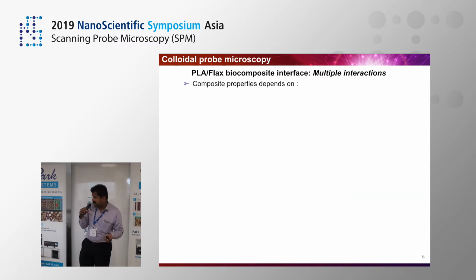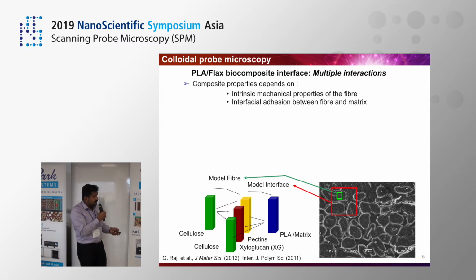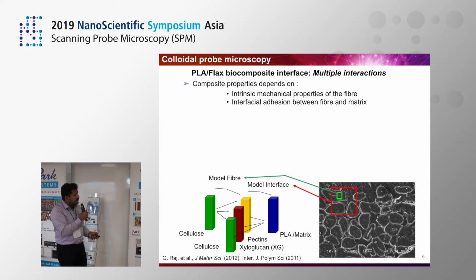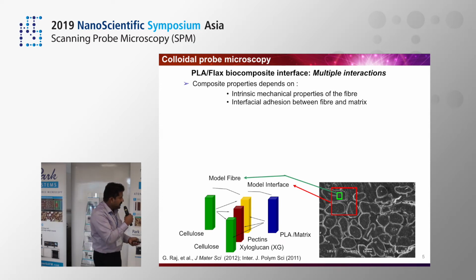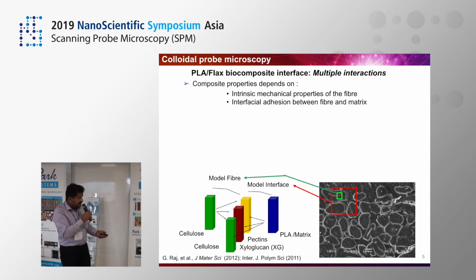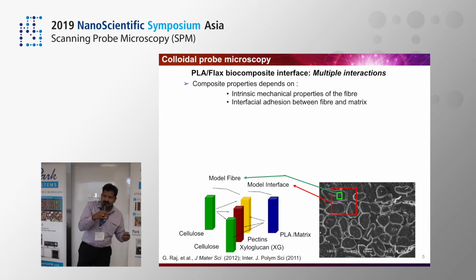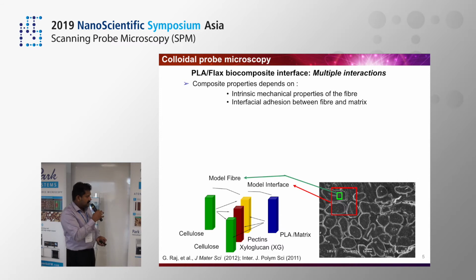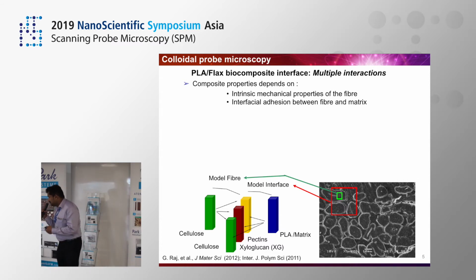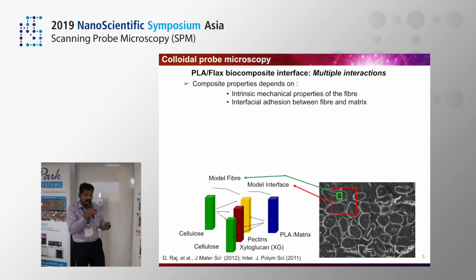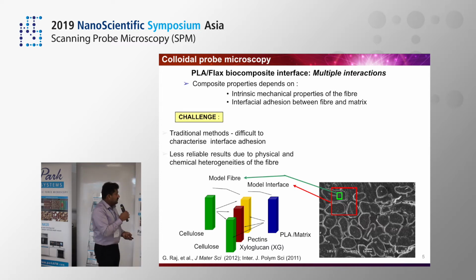So if you take this flax fiber and put it in a polymer matrix, the composite properties depend on the intrinsic mechanical properties of the fiber, as well as the interfacial adhesion between the fiber and the matrix. Now, the intrinsic mechanical property of the fiber is governed by the interactions between different polysaccharides, between cellulose and pectins in the cell wall. And if you look at the interface between the fiber and the matrix, it's not a simple material. There are several interaction possibilities between PLA and the cellulose, pectins, and hemicellulose. So how can we probe these different interactions and how can we optimize the interface to enhance interface adhesion, to finally determine the best mechanical properties for these eco-friendly materials?